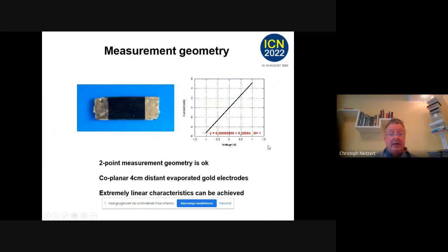Okay, this is the sample. This is about 2 centimeters. It's a large sample, and we have evaporated gold electrodes. Why gold in this case? I will show you. We made a work before where we changed all kinds of electrical metallization, and it's very critical. If you want to have a very stable electrical characterization, contacts are always one of the most critical problems.